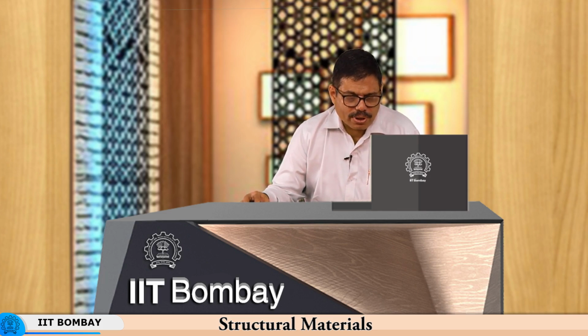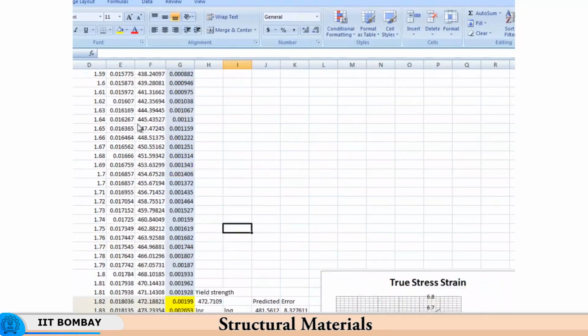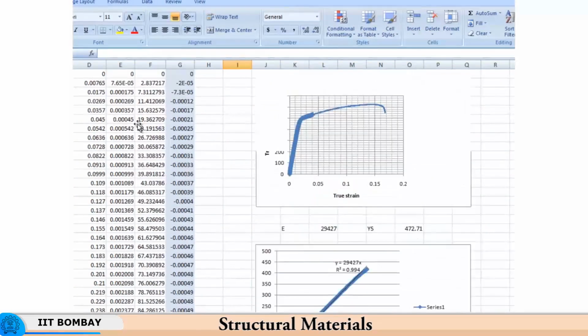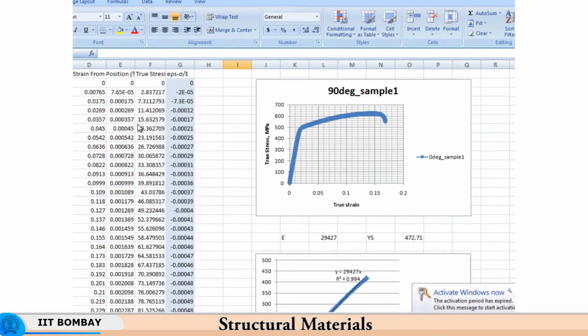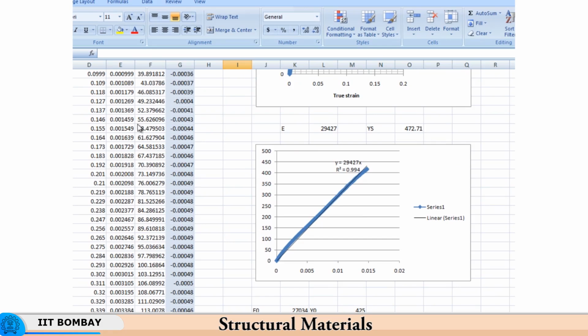So, I will just come to a worksheet where I will show you how it is determined again, so that you have no questions on that. Yeah. So, this is the elastic portion, and you need to determine the slope of this elastic portion. So, Young's modulus has to be first determined, and for that you need to select the elastic zone. So, here we have selected the elastic zone, stress versus strain. So, this is stress here and strain over here. Under elastic conditions, true stress and engineering stress are the same, because true strain is practically equal to the elastic strain. There is no change in the cross section, and therefore, the true strain and elastic strain are practically the same. So, that variation can be in the 7th or 8th decimal place, which is not of interest to us.